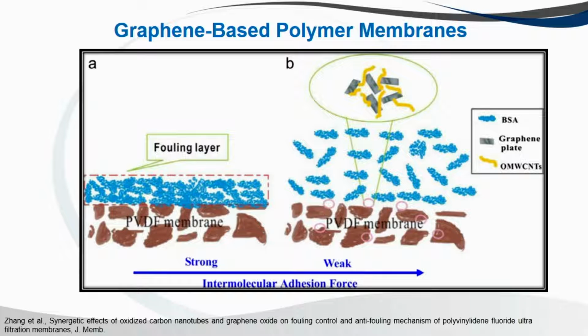The work by Zhang et al. shown on screen demonstrates the effect of oxidized CNT and graphene oxide on the fouling control of BSA and the anti-fouling mechanism of the membrane made from PVDF. There's a strong interaction between the fouling layer and the PVDF membrane, while there is a weaker intermolecular adhesion force between the CNT and GO and the BSA foulant. In this case, nanocarbons are used as fouling control or as anti-fouling agents.